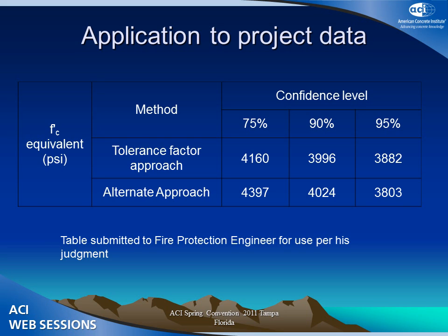Using that equation, if we went backwards from what we had, and accept as fact that there isn't any difference among the floors, our population sample, we ended up using a total of 35 of the data points. Our population sample was very sufficient to have the 10% confidence that this number, if you remember Mike's distribution curve, 10% of your sample might be below that, so you have the 90% confidence that you're higher.